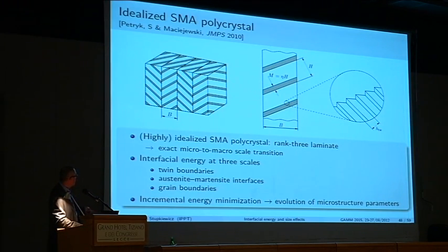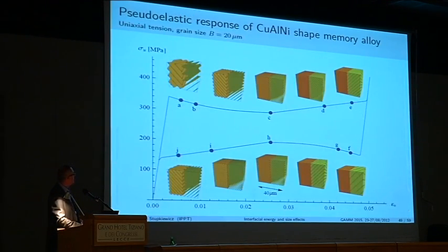Okay, and then we apply the incremental energy minimization framework, and as a result we get evolution of the microstructure. In this simple case, the grain size B is fixed, because the grain boundaries do not evolve, but the thickness of the martensitic plates and the spacing of the twins are the microstructure parameters, and these are determined from the incremental energy minimization. And here is the result. This is the stress-strain response that we get for this specific material. So not only do we get the macroscopic mechanical response of stress in terms of strain, but also at each particular point along this hysteresis loop, we get the microstructure.